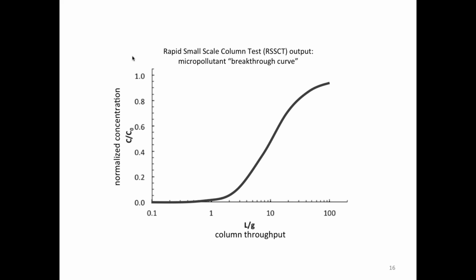I didn't show the data today, but we've done a lot of studies of desorption. So once we run a column study to the point where the material is saturated with the pollutant of concern, then we shut off the pollutant coming into the column and just run the background water through, and we try to look for the release of that pollutant back into the water. And what we see is that, especially in the presence of organic matter, just background organic matter, you don't see a lot of desorption of the pollutants. So they pretty much diffuse into the pores of the adsorbent, and they're stuck there, and then they're continually piled on by organic matter coming into the system. So we don't see a lot of back diffusion or release of pollutants.